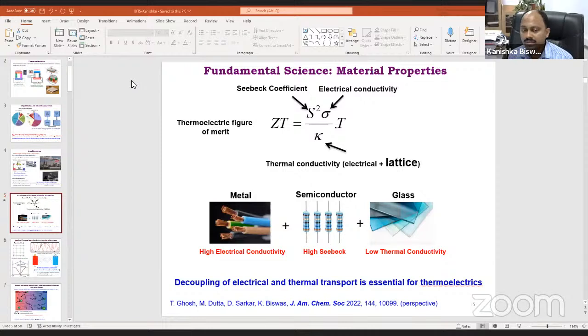So both ways, oxides are no good, but still, if you wanted to work in oxide, pyrochlores are good, which have a complex structure. Once you have a complex or bigger unit cell, it will have some intrinsic phonon scattering. So we can start with around 8 to 9 watt per meter Kelvin. So pyrochlore oxides would probably be a good idea to work with if you wanted to work in oxide. Fantastic.